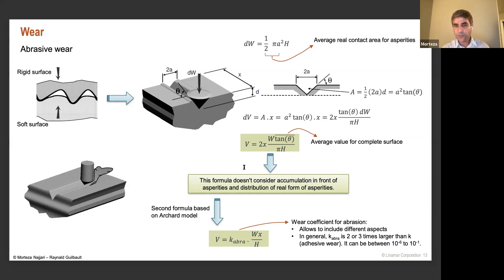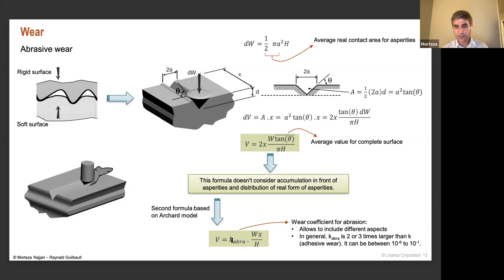This formula does not consider the accumulation of material in front of the indenter, which happens in reality. Archard's model accounts for this phenomenon using the same linear correlation but defines the wear coefficient as an abrasion coefficient. This abrasion coefficient is typically two to three times larger than the adhesive wear coefficient.